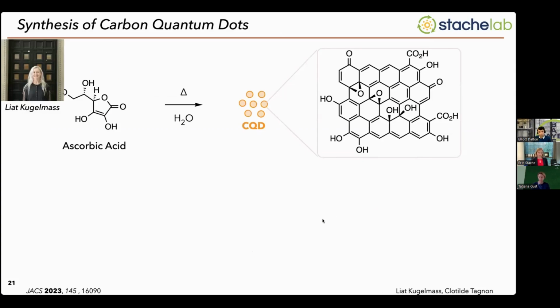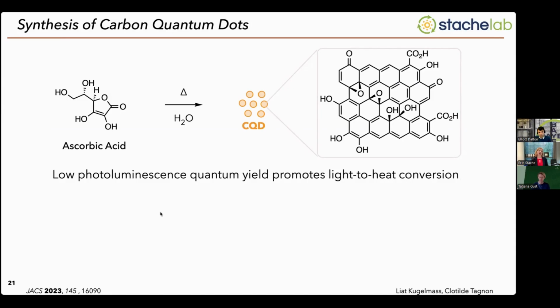And so where we started in this space, we were trying to identify carbon-based photothermal agents. And so Liat got all of this chemistry started. And what she did is she looked through the literature to find materials that had very low photoluminescence quantum yield. And so we hypothesized that if these materials aren't photoluminescent, then they're likely returning back down to the ground state in a non-radiative decay pathway, which means they're generating heat. So converting light into heat. And so what we did is we looked for the worst carbon quantum dots that we could find.